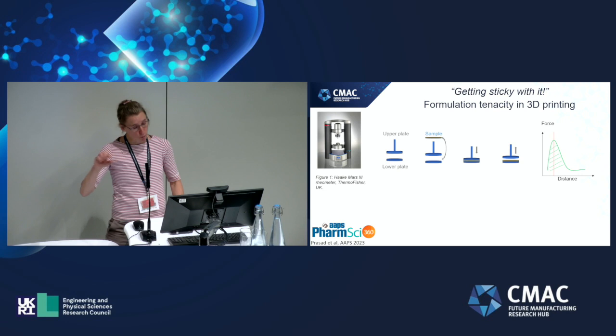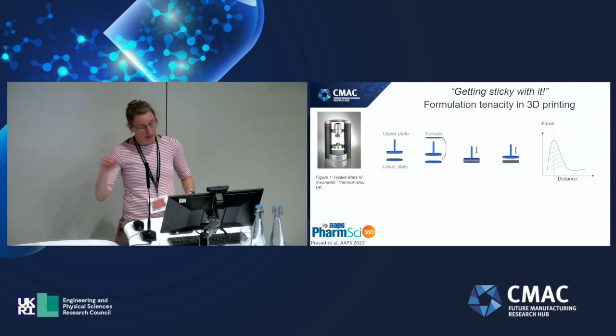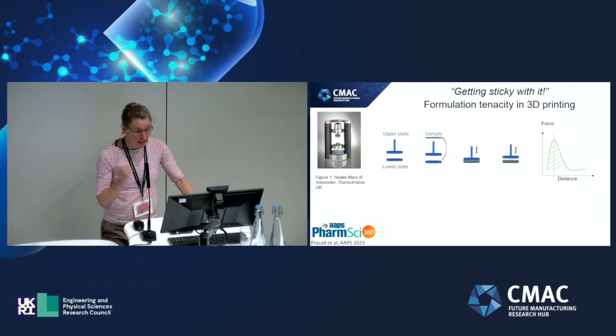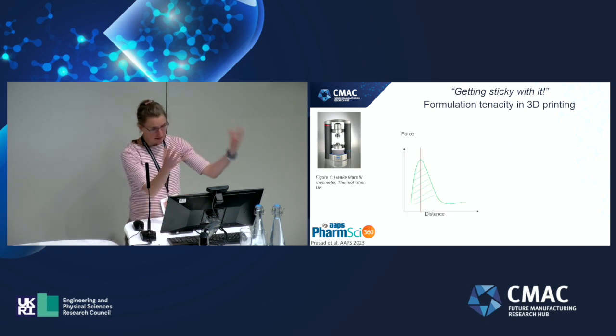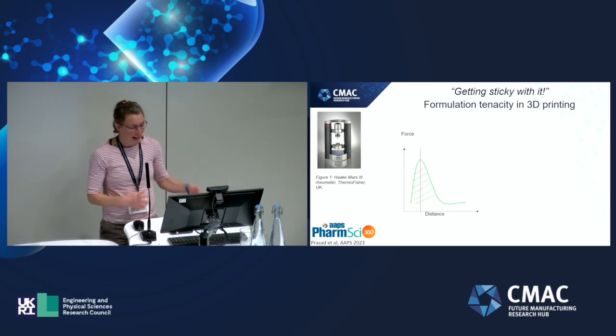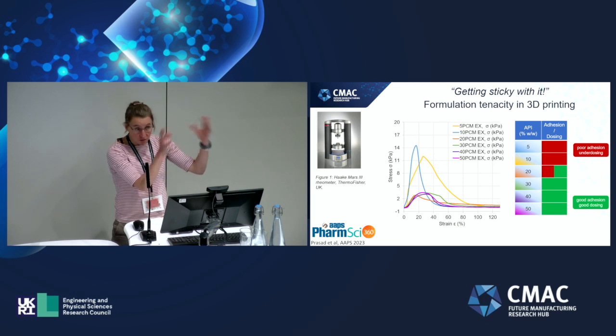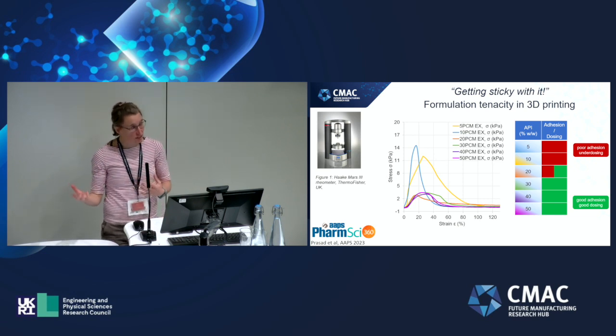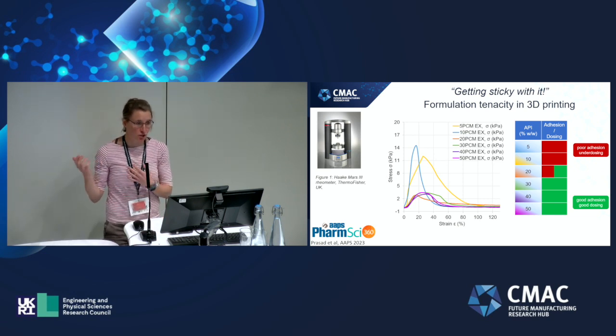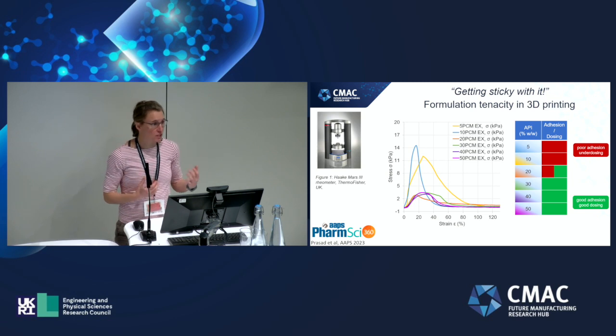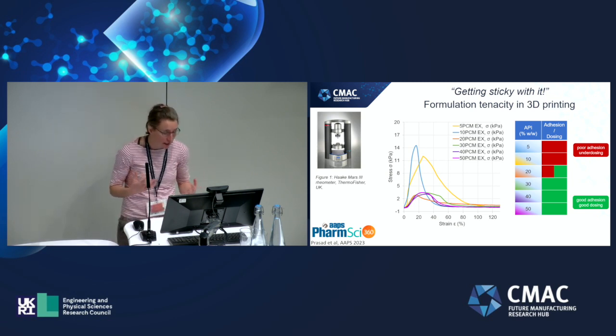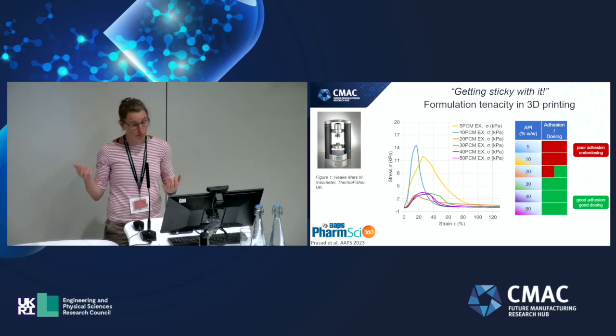to do that, and we're plotting that, the force versus the displacement, and we then get this force displacement curve, and the shape and size of this curve then tells us something about whether the formulation is sticky, whether it shows good adhesion, but it also tells us about the cohesive properties of the material, and cohesive properties may affect the dosing of the material during a 3D printing process.